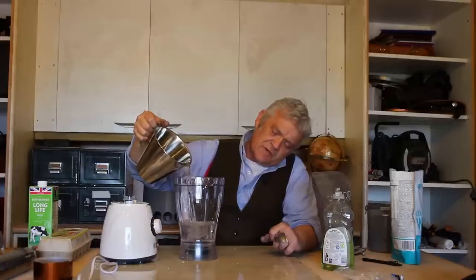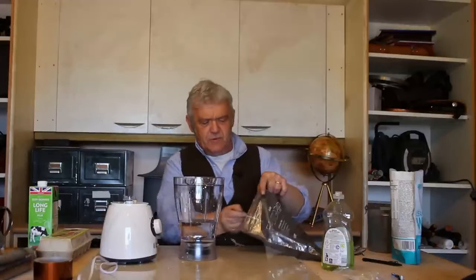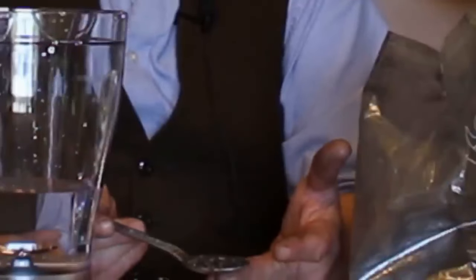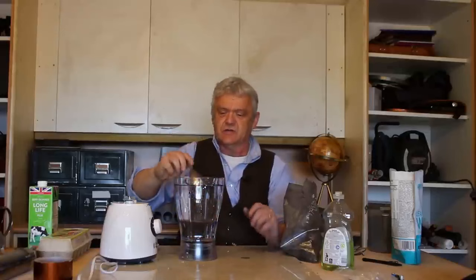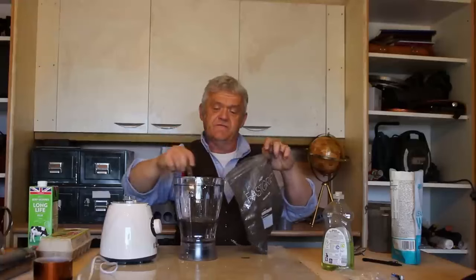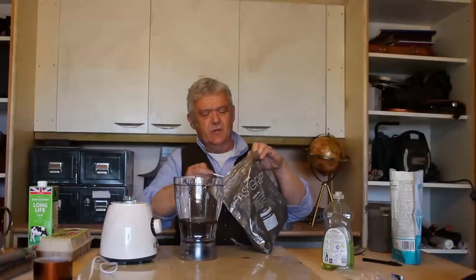So I'm going to add 500 milliliters of deionized water in there and 50 grams of my graphite. Now the graphite I'm using is this stuff. This stuff's actually really rather beautiful. It's about 150 microns across. They used anywhere between 45 to 250 microns. So again, the graphene platelet size isn't that important. However, the bigger the plate is, then the bigger your graphene sheets are and the more conductive it is. So if you use quite a large graphite, then you're going to find it works really quite well. And again, anywhere between sort of 5 grams and 50 grams is going to work in that 500 milliliters of water.